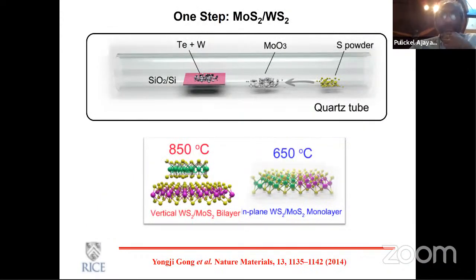Now, there is also another issue. If you are particularly interested in stacking different compositional layers, then either one can form on top of the other, or you can actually form lateral structures, because many of these structures that we are trying to combine in stacking are isostructural. So if you take something like boron nitride or graphene, their lattice parameters are very similar. As they grow, they can not only stack one on top of the other, but they can also get stitched together in a lateral junction. The same story with many of the dichalcogenides. So at the end of the day, when you're trying to grow them, you end up with all these mismatches of various structures, both in plane and out of plane.